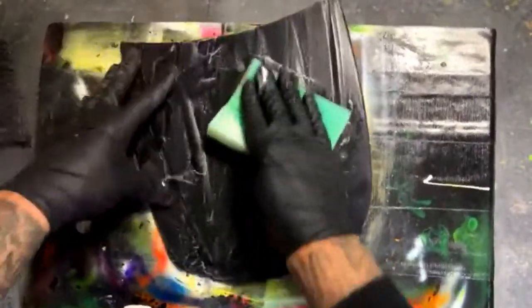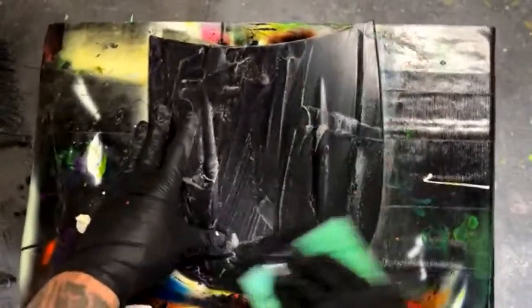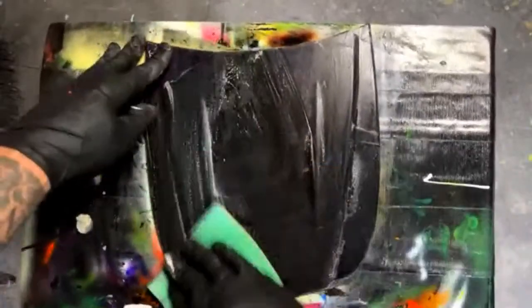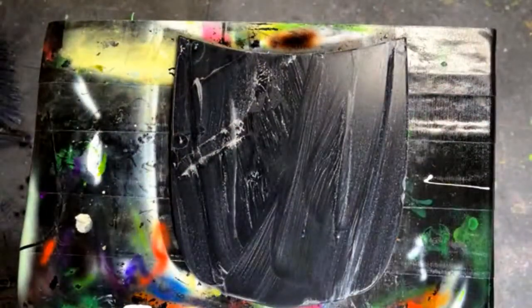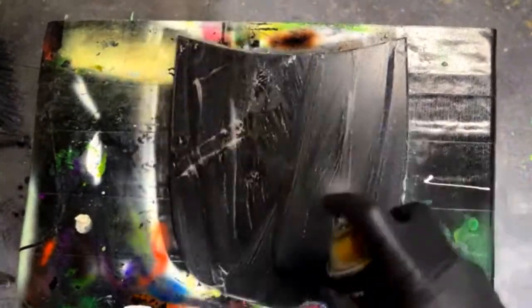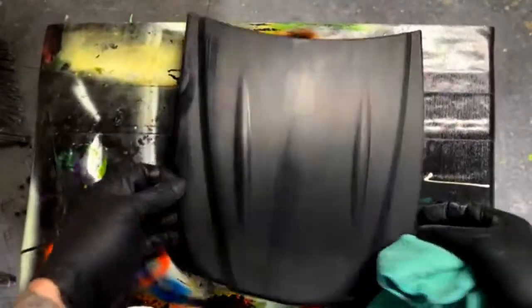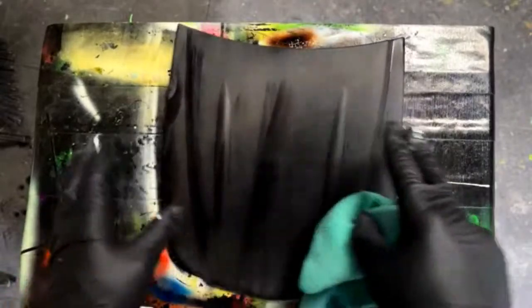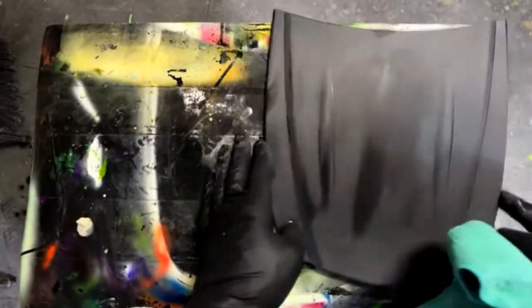I'm just using some 600 grit right here, sanding it wet. This is just one of the small practice limelight hoods, scuffing it down to make sure we got good adhesion so that the paint is gonna stick to it. Looks like that's pretty good — I'm gonna go ahead and take some glass cleaner, just regular any kind of glass cleaner. Looks like I got that scuffed down pretty good, got the gloss knocked off of it. It's gonna give us good adhesion for the paint to lay down. If you don't do that you'd probably end up peeling your paint edges.